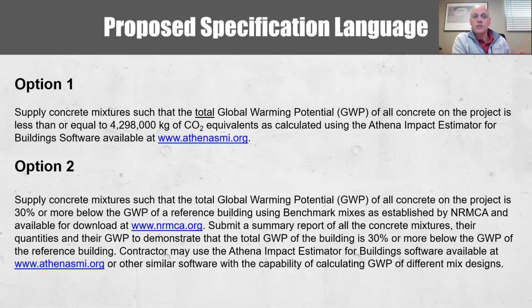Again, allowing for some mixes, let's say post-tension slabs that needed a higher early strength and couldn't have a significant SCM replacement, that could be higher than the benchmark. But other concretes like the mat foundation, basement walls, and so forth could have a significantly lower impact because they could have significantly higher SCM replacements.